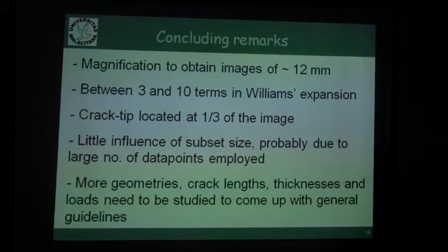To conclude, the best results were obtained with a magnification such that the field of view is 12 millimeters, using not just one or two terms, but 3 or more terms.